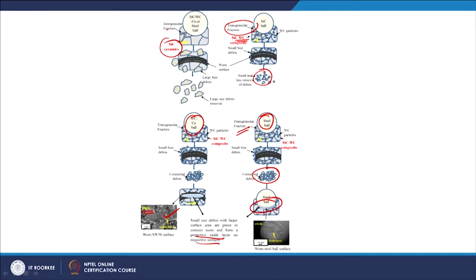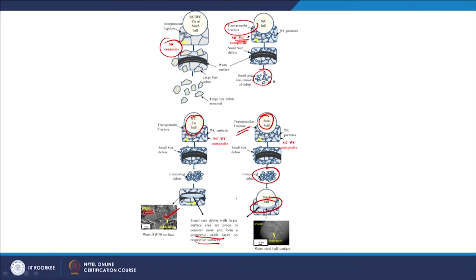So, the layer is observed either on the ball surface of the steel or on the disc which was worn against the tungsten carbide cobalt. They show certain layers, whereas such a layer is not observed when these composites were worn against silicon carbide. Against silicon carbide, it is purely the fracture. The material is removed only by the mechanical fracture and then the resultant grain pull out.